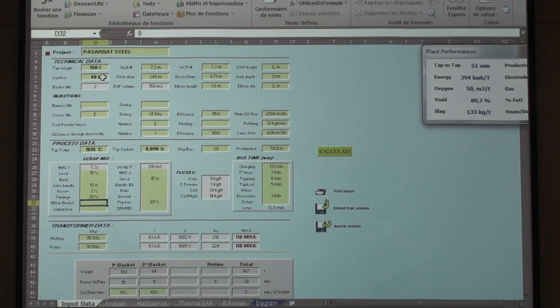In the case of the Pasargat project, they will have a similar line also, and the slag is cut off on top of the hot metal. Then we take it to the EAF, but still slag remains on top of the hot metal. We can pour out the hot metal in a proper size, and then we can take it back, and we cannot pour the slag with the hot metal, only hot metal. That is one of the philosophies, I think.